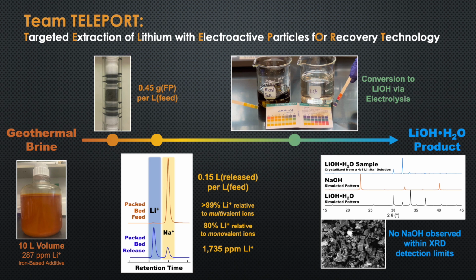In summary, Team Teleport uses a high-capacity solid particle packed bed to selectively extract lithium from brine and release it into an order of magnitude smaller solution with excellent selectivity against other ions as analyzed using ion chromatography. Extracted lithium is converted to lithium hydroxide via electrolysis as evidenced by pH and ion chromatography, while also regenerating the oxidizing agent used to release lithium from the packed bed. Finally, X-ray diffraction analysis of the crystallization product reveals a lithium hydroxide monohydrate product resulting from the ready-to-scale Team Teleport approach.